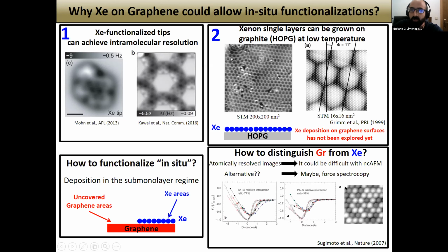Well, it has been reported that when we have different atomic species on a surface, if we perform atomic force spectroscopy on top of each of them, we can find differences in the maximum attractive force measured. And if these differences are large enough, I mean, if we have a large relative interaction ratio, we can distinguish each species. But the question is, how much is this difference between xenon and graphene? Is it large enough to allow us to distinguish graphene from xenon just by performing force spectroscopy? Well, this is one of the things that we want to study in this work.